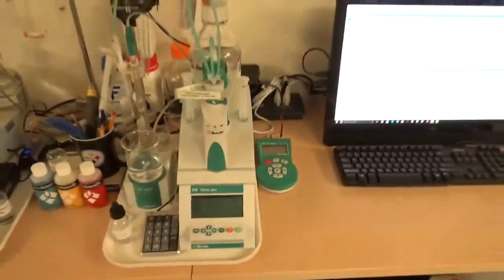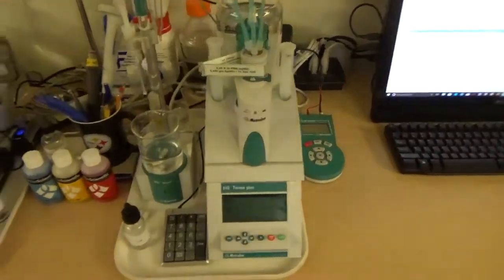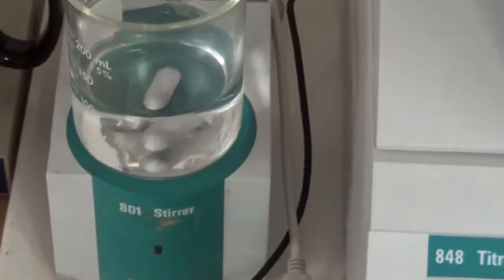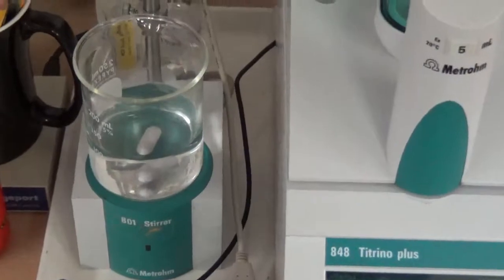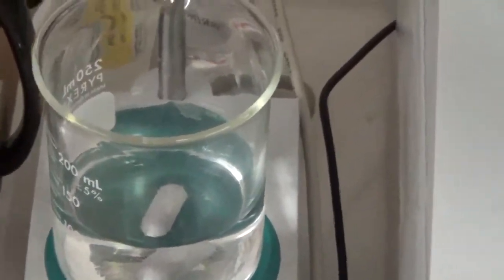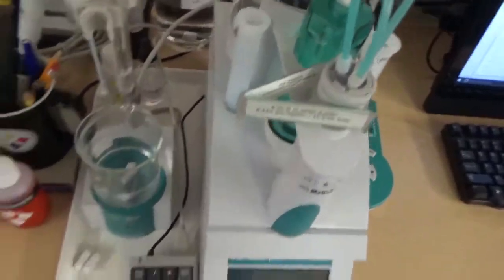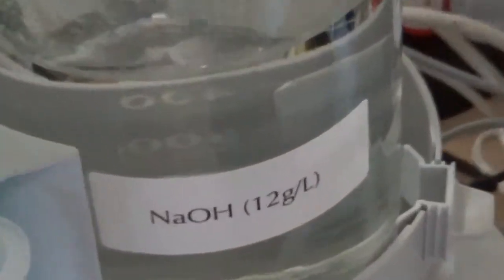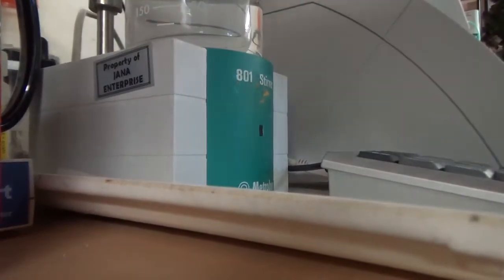Now when we do the acid-base titration, we use this 848, as I said, 848 Titrino Plus. It's attached to the 801 stirrer. In this case, it's a magnetic stirrer, so you have to put a magnetic stirrer bar inside the beaker. And here I'm going to show you a simple acid-base titration. I'm using sodium hydroxide as my titrant, and I'm going to put little drops of hydrochloric acid to show the acid-base titration.